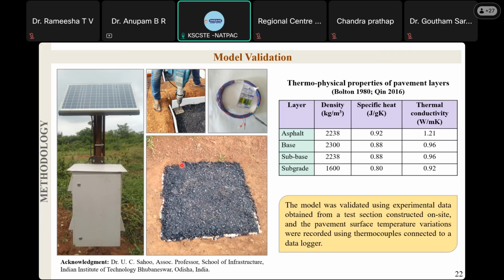One more thing, what about the rainy season? Will it have some effect on this? Yes. In the rainy season, the temperature observed is less, both for normal pavements and this cool pavement. Basically, we aim for this cooling action to come into place when the pavement temperature is higher. For example, most technologies are designed so that when the pavement temperature is above 40 degrees Celsius, they should come into action. At lower temperature, suppose the temperature of the pavement is 30 degrees Celsius, we don't have a problem.